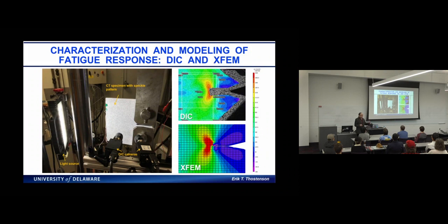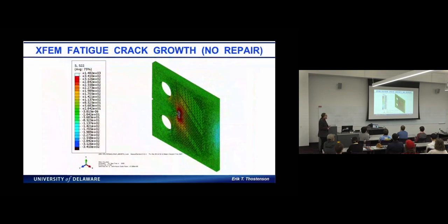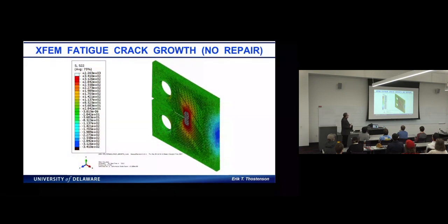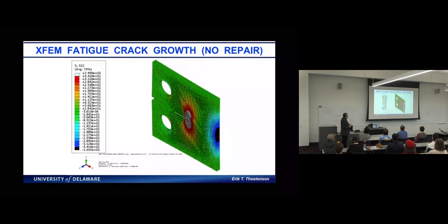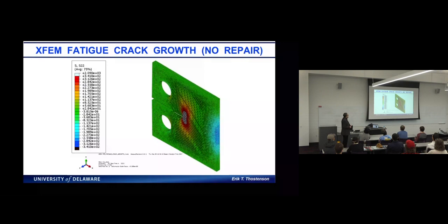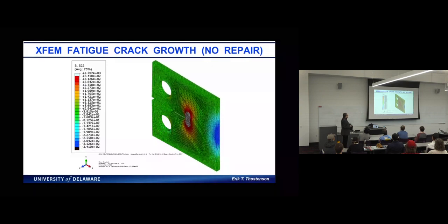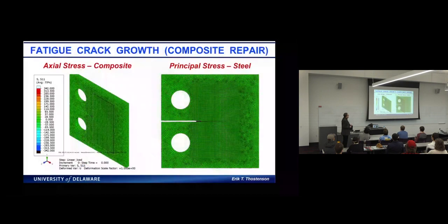Of course, we study this in the lab and have also done a lot of modeling of the crack. This is an extended finite element simulation, but we've also done digital image correlation, and you can see the stress concentration at the crack tip. And I like these videos. This is if we have no repair, and of course you see that high stress concentration at the crack tip. And this is our simulated part where we use that simulation to design our repair.